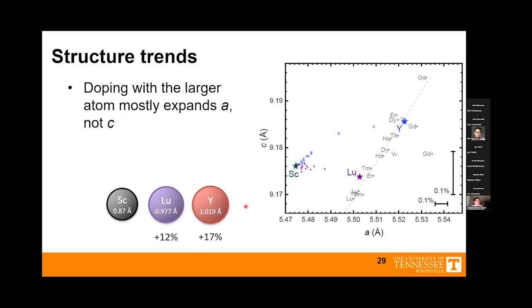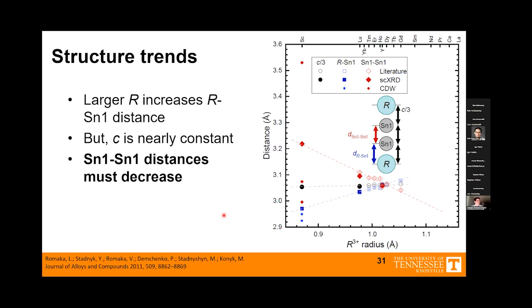Clearly, these bigger rare earth atoms, I guess they're not lanthanides, aren't increasing the C lattice parameter as much as you'd expect based on their size. So what's accommodating those larger rare earth atoms? Well, I argue that if we're putting a bigger rare earth atom in, we've got to move the tin along the C axis away. So if we look at our stack of rare earth and tin atoms along the C axis, these are in the channels of the kagome network. This distance here between tin 1 and the rare earth is going to grow as we put a bigger rare earth atom in. And you see that bigger rare earth atom radius, bigger distance between them. But because our C lattice parameter doesn't move as we put bigger rare earths in, the tin-tin bond distance has to decrease. And we see that in our single crystal diffraction data.